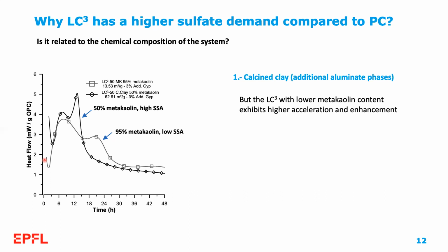And for a long time, we believed that it was the alumina introduced by the addition of metakaolin, an amorphous aluminosilicate, into the system. The problem is that this correlation is not systematic, as we see in the plot here on the left. We have a system with 50% metakaolin addition, which exhibits a higher sulfate demand than a system with 95% metakaolin addition. We can see that both systems have the same gypsum addition, and in this case, the peak occurs earlier in the system with lower metakaolin.